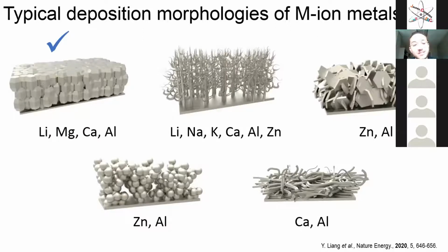So what we are looking for is this homogeneous deposition and stripping, which is very good, and this will keep the battery working. Then, depending on the electrolyte chemistry and cycling conditions, we have the metal dendrites that I talked about before, and then random flakes, spherical deposits, or wires. We want to avoid these because they will cause short circuits and loss of energy density during cycling.